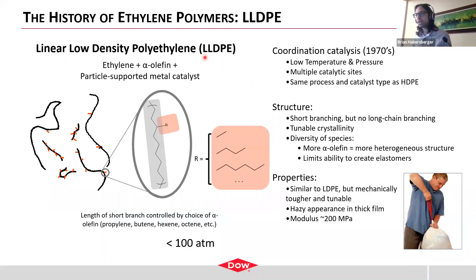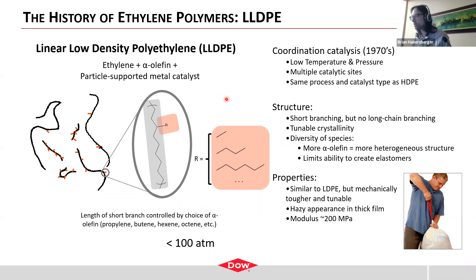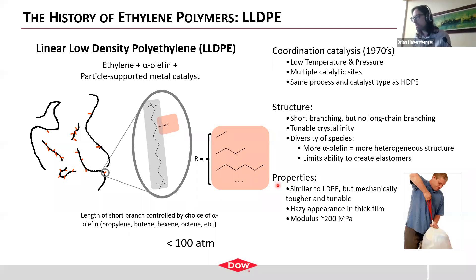LLDPE — linear low-density polyethylene — is actually made by completely different chemistry than LDPE. It uses a particle-supported metal catalyst, similar to HDPE, but now we're co-polymerizing an alpha-olefin, which could be propylene, butene, octene, or hexene. The structure does have short-chain branching, which can tune crystallinity. However, you don't get a uniform distribution of the co-monomer across all polymer chains, which limits your ability to make highly elastomeric products. The properties are generally similar to LDPE, but much more tunable and therefore potentially much more mechanically tough. They are relatively hazy and have a comparable crystallinity and modulus to LDPE.